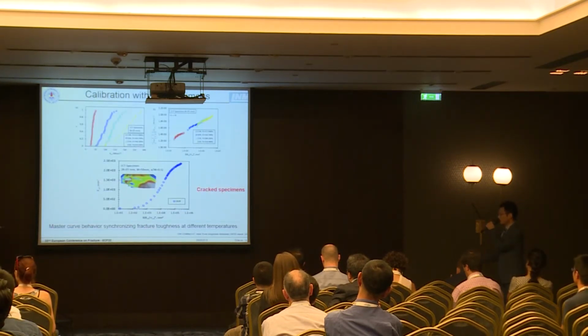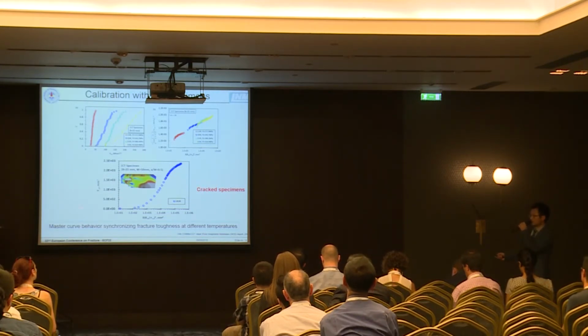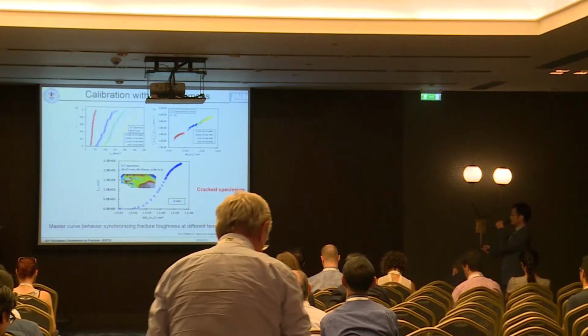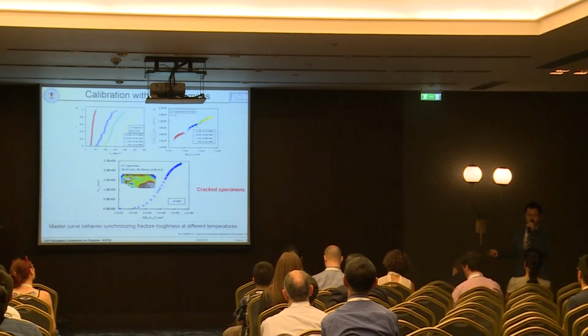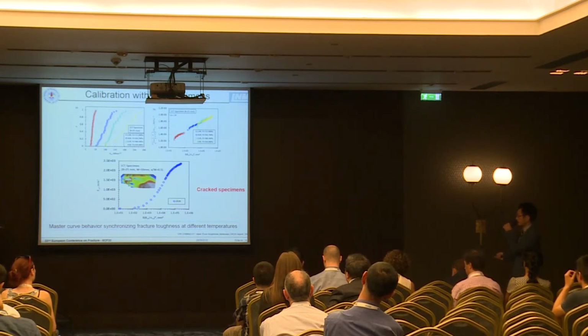And also, our model is validated and calibrated with the Euro toughness database, which is for reactor pressure vessels. Similarly, at different temperatures, we can also see the data fall almost on the same curve. This also confirms that the advantage of our model is that these two parameters are temperature independent and can be calibrated for further applications.